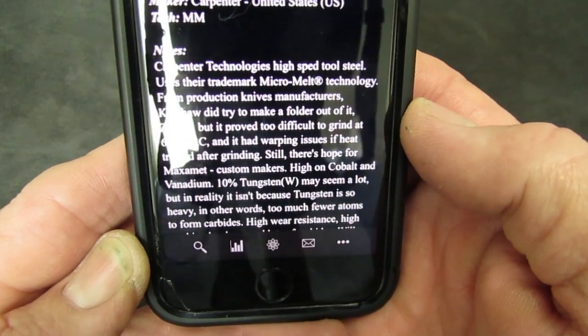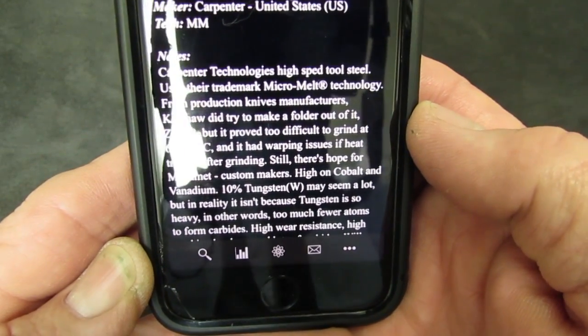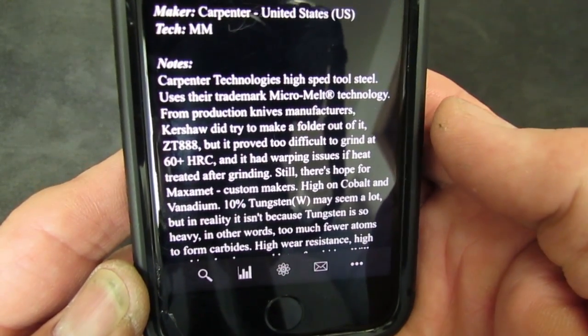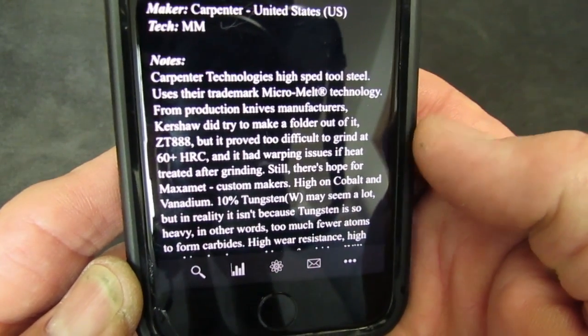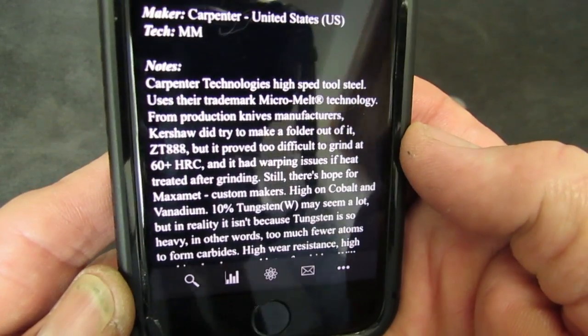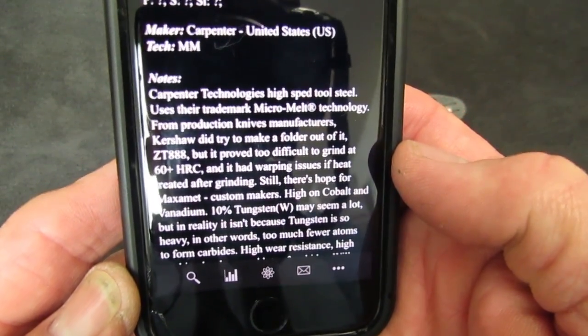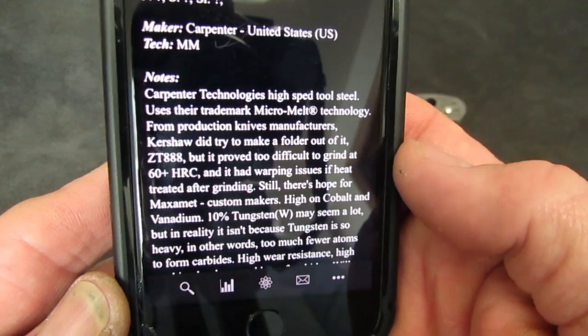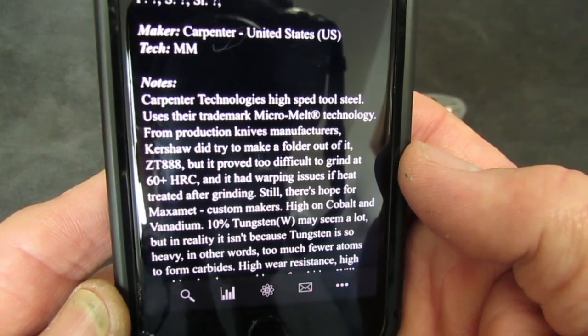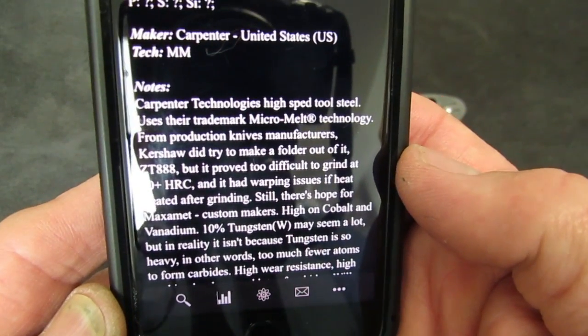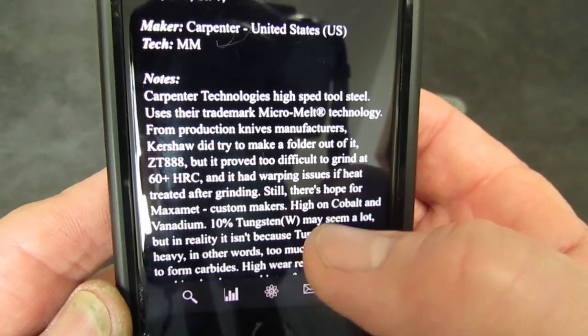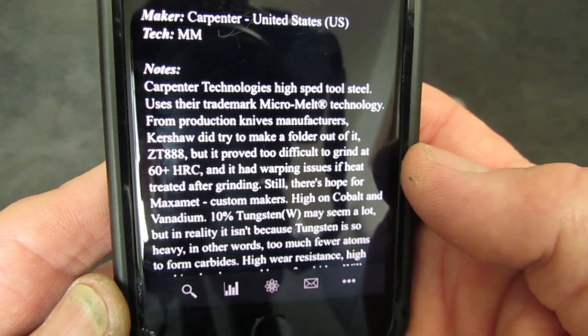Carpenter Technologies high-speed tool steel uses their trademark micro melt technology. That would be putting marketing spin on that. Micro melt is the old process for powdered metal in Carpenter's realm. The Gen 2 process that they use for CTS 204P and other more current steels is better. Okay, moving on. From production knife manufacturers, Kershaw did try to make a folder out of it, the ZT 888, but it proved too difficult to grind at 60 plus HRC and had bad warping issues if heat treated after grinding.